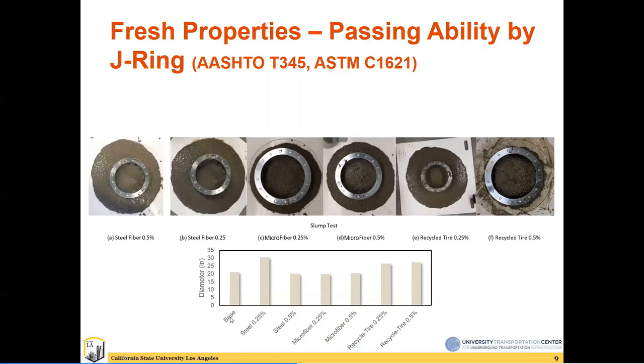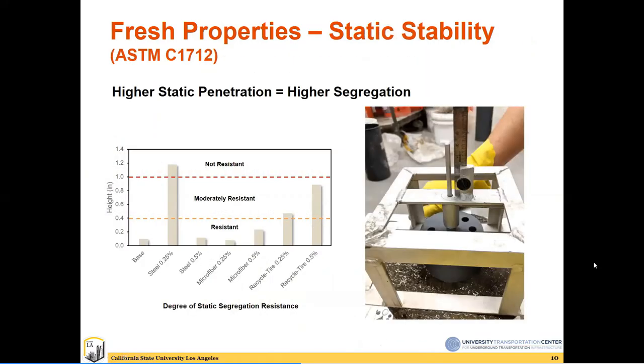So what we are doing, we have a base SCC mix without any type of fibers, and then we compare the flowability or the passing ability by the other mixes that contain different types of fiber at different dosage by volume of the concrete. Again, these are still preliminary results, and will include more comprehensive results later on.